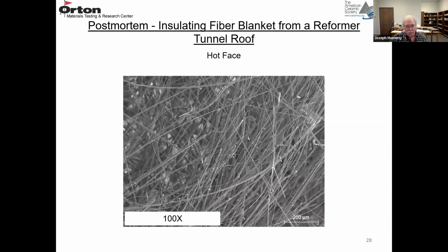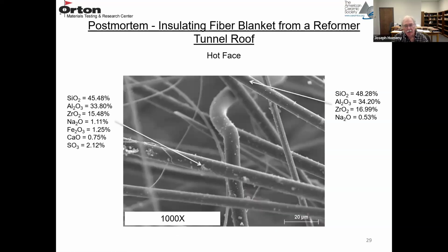And if you look at the fibers, this is 100X. This might be some spherical shot particle right here. Maybe there's another one over here. And this is a 200 micron marker. So these are pretty fine fibers. And if you increase the magnification, you can see how they're starting to degrade. There's a deposition on the surface of these fibers.